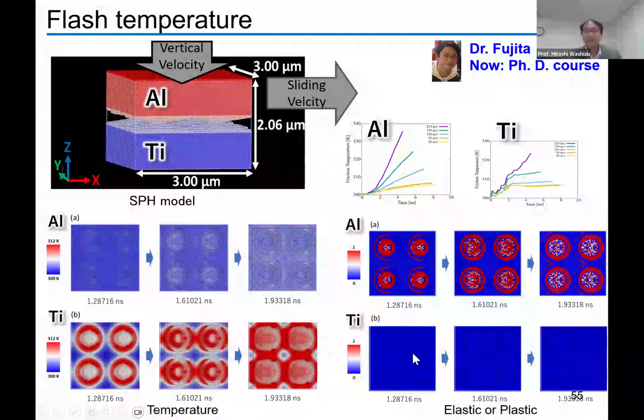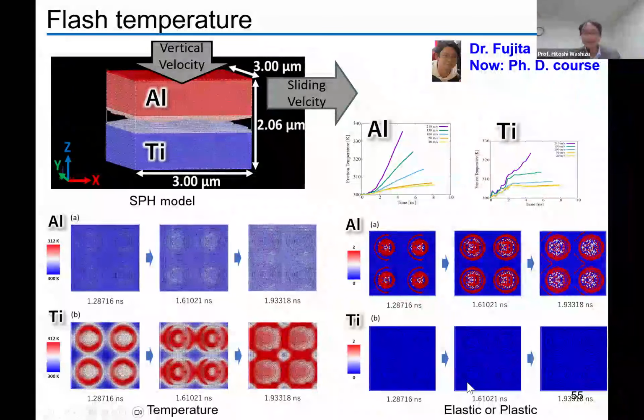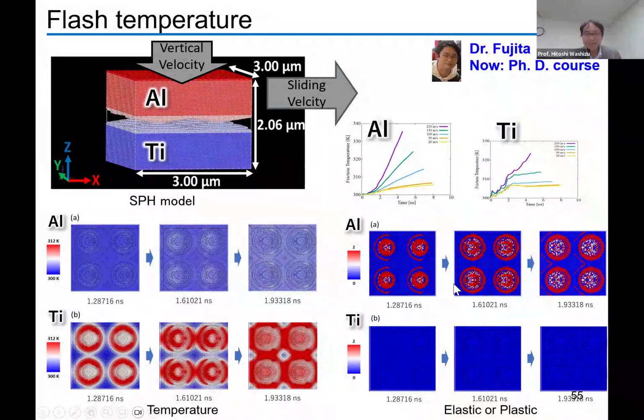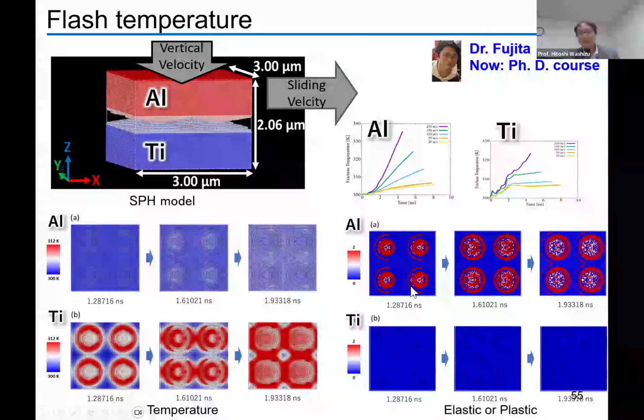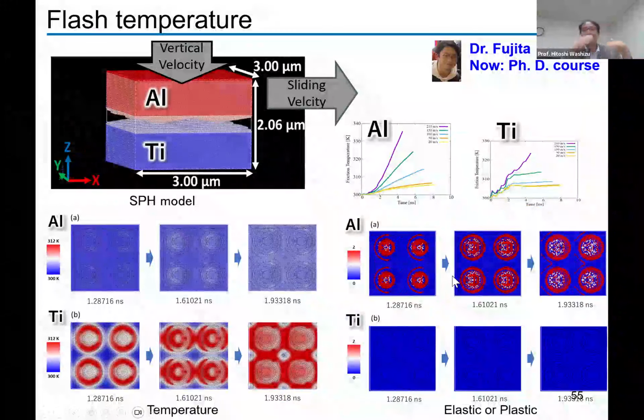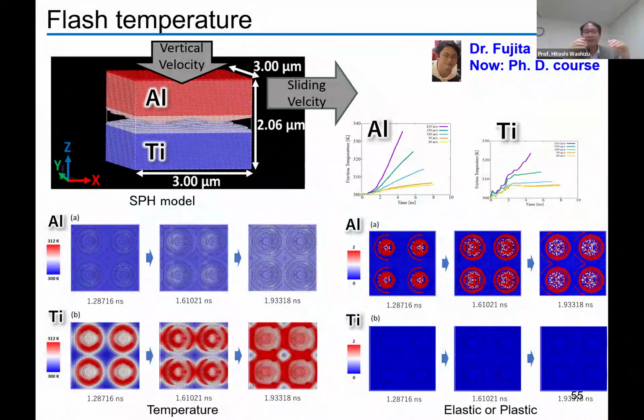On the other hand, titanium is a much more elastic, much harder material, and aluminum is a much softer material. So this is elastic or plastic. If it is going to the elastic part, we put some red sign, and the titanium is elastic, and aluminum is plastic. So we can distinguish what's happening in the real contact area, including the heat dissipation and heat conduction